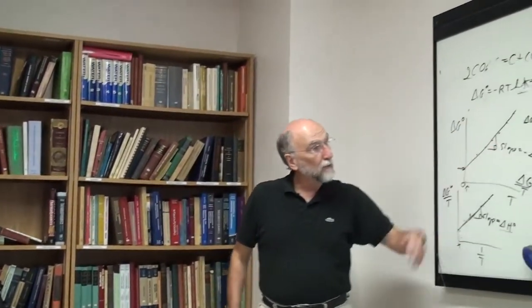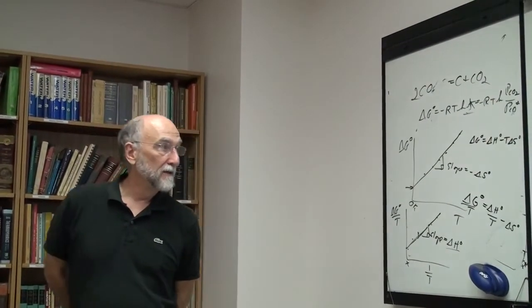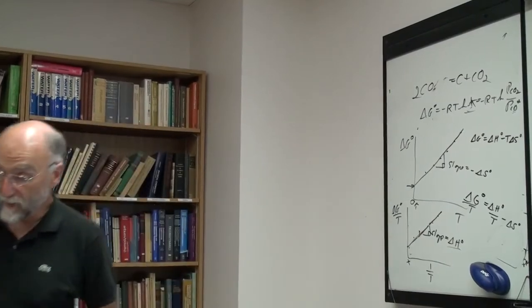This is a way of measuring entropy. Now this doesn't measure S absolute, this measures delta S. It measures delta H. It measures the change in entropy for the process, it doesn't measure the absolute entropy. This method of measuring entropy, by measuring the Gibbs energy change, by setting the system up at equilibrium and taking the slope, is called the second law method of measuring entropy.